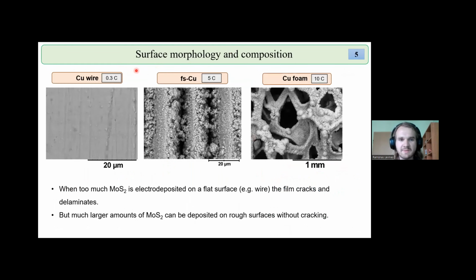So molybdenum sulfide had been deposited on various surfaces. On copper wire, the SEM images show that the morphology is fairly flat and featureless. On the femtosecond laser ablated surface, we notice the deposition of micro or even nanocrystalline crystallites. And on a copper foam, we don't really investigate the nanomorphology, but we see that the overall coverage of the foam does occur across the entire foam, as far as can be told from SEM images. The reason for using these different substrates is also that different catalyst loadings, which are represented here by charge passed through the system, can be obtained. Because if too much material is deposited on a flat surface, that is to say, too much charge is passed through during electrodeposition on a flat surface, this film tends to crack and delaminate from the surface.